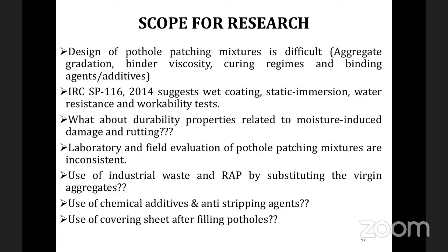So someone can assess different pothole patching mixtures, maybe the Kandal mix or ready-made mixes. There are a lot of ready-made mixes available in the market, like Hinkol, Durapave, Permapatch, Road Bond, and the Kandal mix. You can take some 5-6 materials along with the tests suggested by the IRC. You can also work on moisture damage through ITS, and rutting through the wheel tracking test.